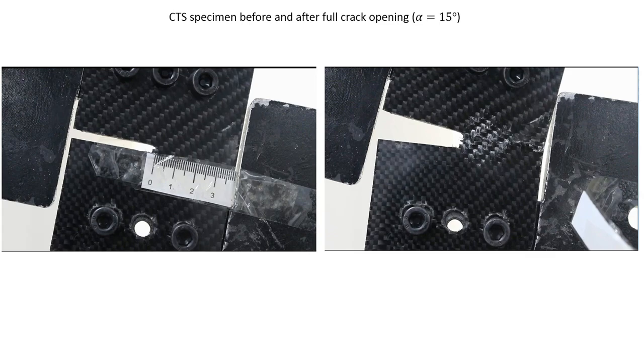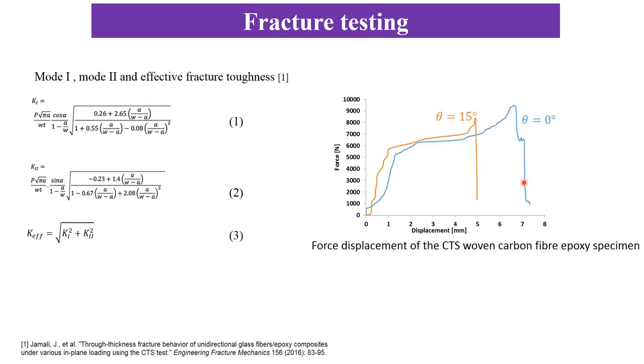These two photos show the CTS specimen before and after applying the fracture testing, when the angle is 15 degree and mixed mode 1, mode 2 loading is applied on this specimen. The crack growth angle here was measured to be almost 7 degree. Here on the right hand side you see the force displacement for this fracture testing when the angle is 0 degree, pure mode 1, and 15 degree. The force is measured from the load cell and displacement from the crosshead.